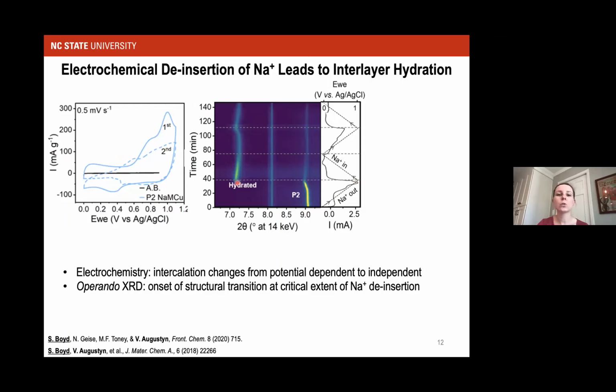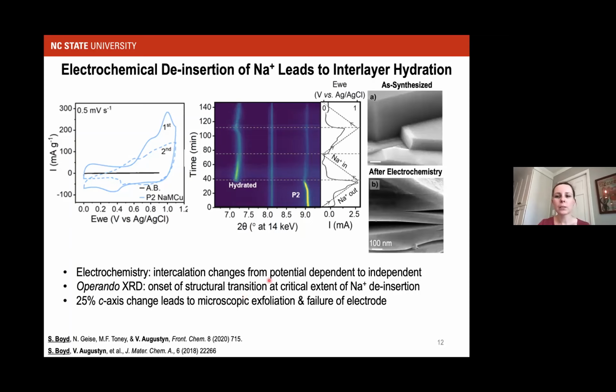Water comes in to basically offset the loss of sodium ions. We think it's driven by the need to offset the repulsion between oxygens within the layer. This happens very quickly, very discretely. There's no continuation of this process. And then you're left with this hydrated phase that is still electrochemically active, but in a much more continuous manner, in the sense that this interlayer spacing changes more like a solid solution type process. What happens at the electrode particle scale is that this phase transition is about a 25% c-axis change, and we actually see microscopic exfoliation that leads to failure of the electrode because these particles become electronically disconnected from the electrode.